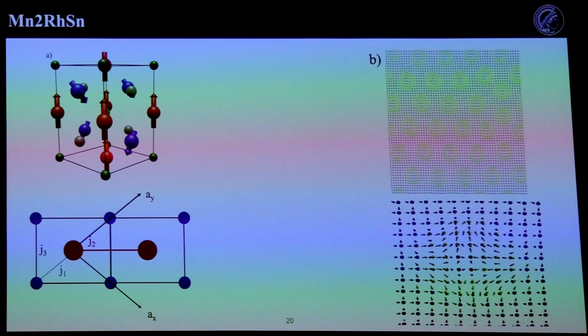Simple, not on a quantum level like Christina, but we take this manganese 2-rhodium-tin and we just flatten it down to a simple model with these 3 exchange interactions we have. And when we're above the spin reorientation, we get these very nice antiskyrmions that form, they're ferrimagnetic. What's nice about being ferrimagnetic is that they are almost like an antiferromagnetic, so they should move closer like antiferromagnetic systems, but they also have a very large spin moment, so you can still detect them in things like TEM and other systems.